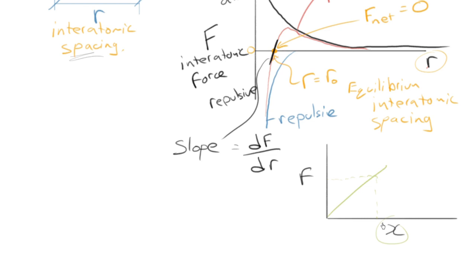So when we're still elastic, there's some kind of a relationship between force. In fact, we could apply a certain force and observe the resulting displacement. So the conclusion, which I hope is not a big stretch of your imagination or your understanding, is that in fact there's a relationship then between the Young's modulus. This is the Young's modulus. Okay? And this interatomic force separation curve. And the relationship is in fact this. It's that Young's modulus is directly proportional to the first derivative of the interatomic force separation curve at r equals to r0. And that is actually an important result.